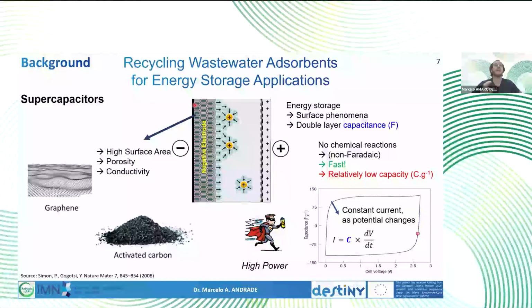So you want this electrode to have a very large surface. So you need very porous materials, you need light materials with high surface area and high conductivity. And that's why activated carbon or graphene-based materials are ideal for these types of applications. So they are called capacitance and they rely on non-Faradaic phenomena. Basically, there are no chemical reactions. So once you shift the potential, you will see a constant current.